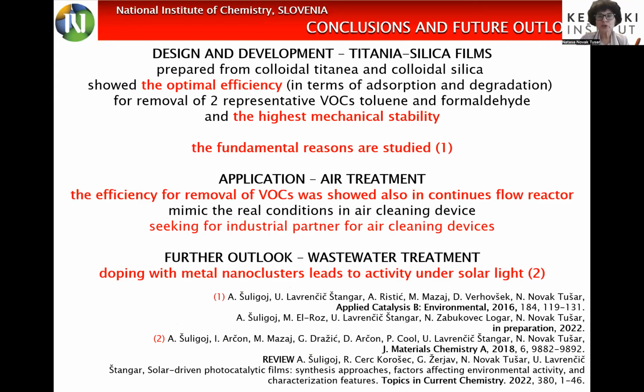So if we look at the conclusions and further outlook, what we did up to now is that we prepared a colloidal titania and colloidal silica coating with optimal efficiency in terms of adsorption and degradation for the removal of two representative VOCs, toluene and formaldehyde, and we have the highest mechanical stability. For the moment, we are still studying the fundamental reasons for this. Our second publication concerning this is in preparation. The first one was published in 2016.